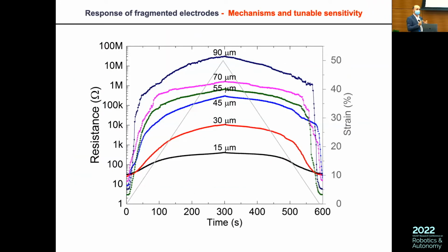And what is interesting is to see this. If I take a film of CNT paper with cracks like this and apply a strain, going from 0 to 50% strain and back to 0, with one of these thicknesses, for example a 90 micron CNT film, what you observe is an initial resistance of around a few ohms. Then when you start to increase the strain, you have a huge increase in resistance, going, let's say here, to 10 megaohms, but you never lose the conductivity. You always have a conductive system. But you have a huge change in resistance, and then you come back to the initial value when you reduce the strain.